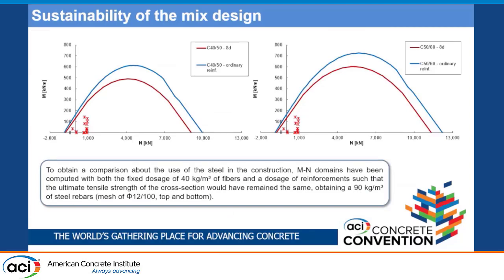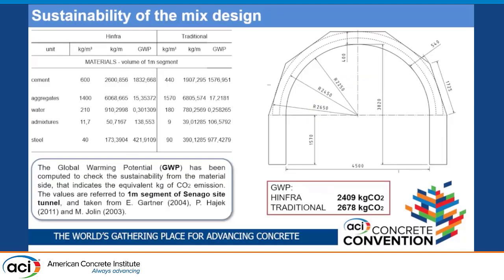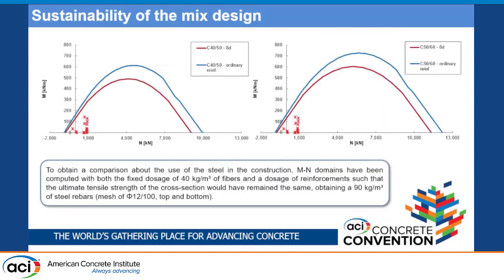So how did I find the values of the reinforcements? The red curves are the moment, axial force M-N domain of a cross section of this shape here. So 40 centimeters of height and 1 meter of length. The length is the segment of the tunnel. So with 40 kg per cubic meter, we have also tested some beams and cubes. We have seen that the compressive strength is about 40-50, and the characterization according to Model Code of this mixed design has led us to this 8D. So it's quite high tensile strength. So we have seen that this material is able to satisfy the safety of the tunnel.